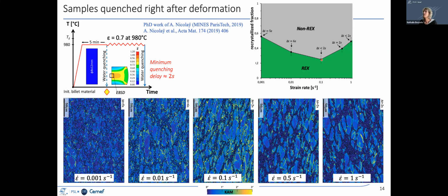The explanation that has been provided for this is that if you increase strain rate, you shorten the deformation time. And the reason for getting a lower recrystallized fraction is actually that the deformation time is shorter and shorter. And here, with increasing, again, strain rate, you have another effect, which is at strain rates higher than 0.1 per second, then you have self-heating issues. So temperature is increasing during deformation. And because of the higher temperature at the end of deformation, then you accelerate again the recrystallization phenomena. So this is the explanation which sounds logical and that you can find in the literature.